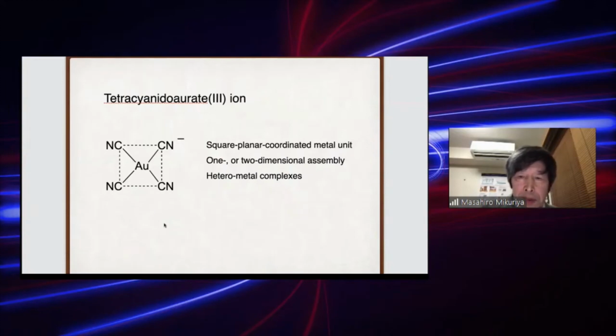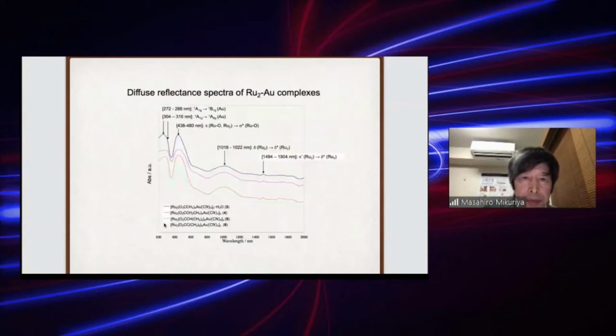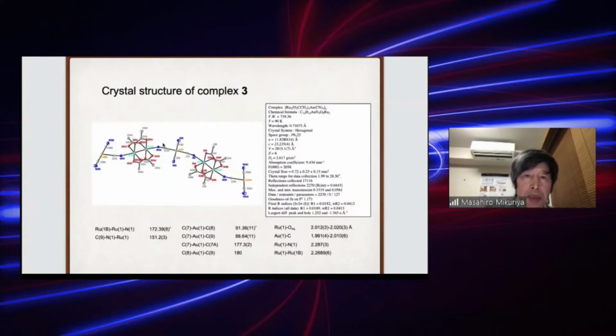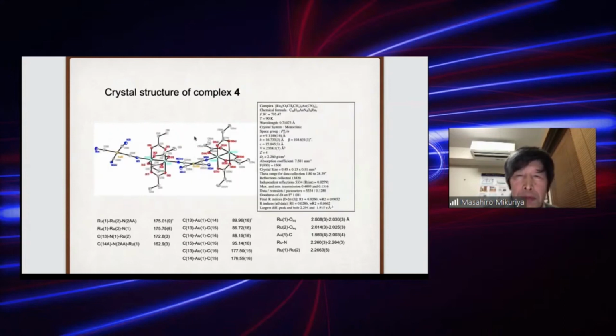So then we used carboxylate ion. We connect ruthenium units, and we can see the presence of carboxylate here, and we obtained the single crystal, and we found chain structure here. In this case, acetate case, we obtain this one is trans binding for ruthenium unit. For propionate, we obtained similar structure, but in this case, this one binds in cis position to this ruthenium unit.